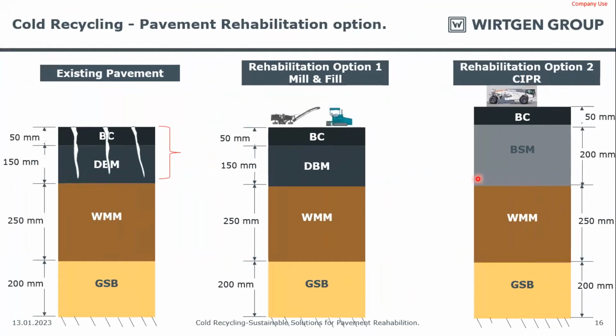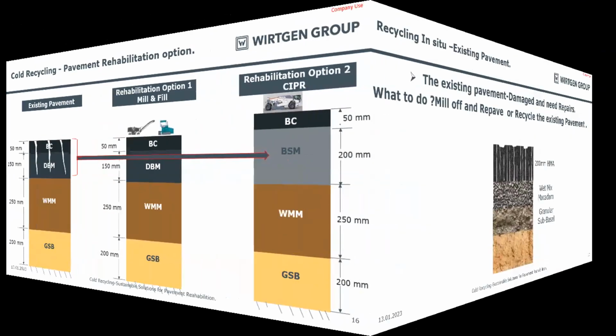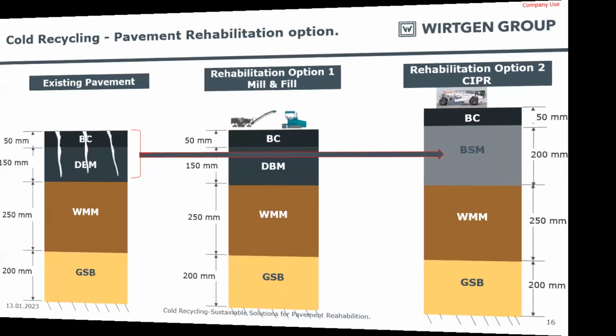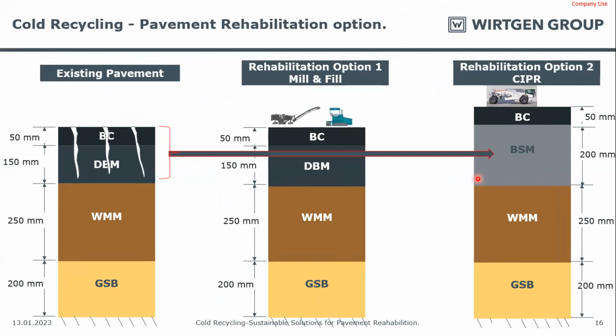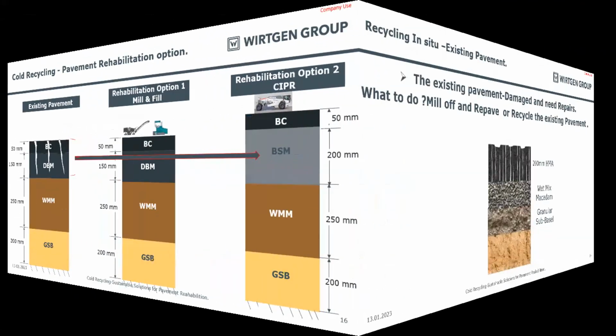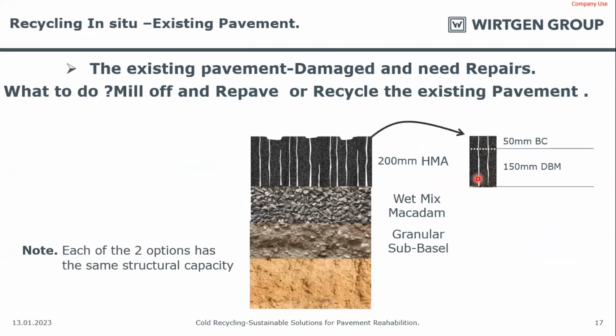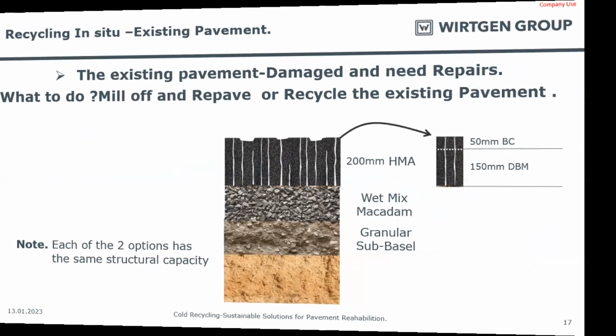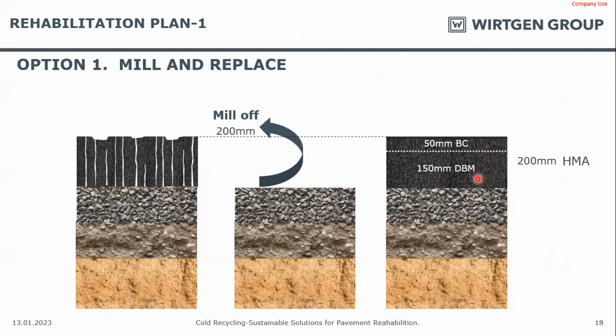So as I said, you have two options. You can decide based on the project economics. Option one is mill and fill: mill the existing damaged asphalt layer and use 30% back in DBM. And the second is the BSM layer, where you completely reuse the complete damaged asphalt layer back into the system, and we seal it with the 50 mm BC layer. Each of these two options, either mill and fill or CIPR, has the same structural capacity. So the first option is mill and fill, and the second option is CIPR.